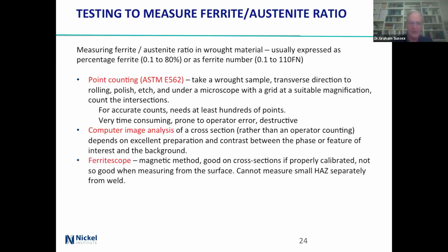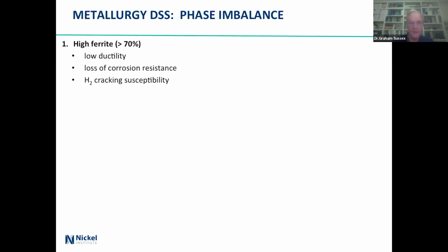Or you can go for a magnetic technique, and you can get quite close to a weld and get good results from that. But it's not quite as accurate because it doesn't detect very small areas. You have to properly calibrate it, and it's not so good if you're measuring on a surface that's rough. And you can't measure small HAZ separately from the weld, whereas you can with the point count. Just some comments about that.